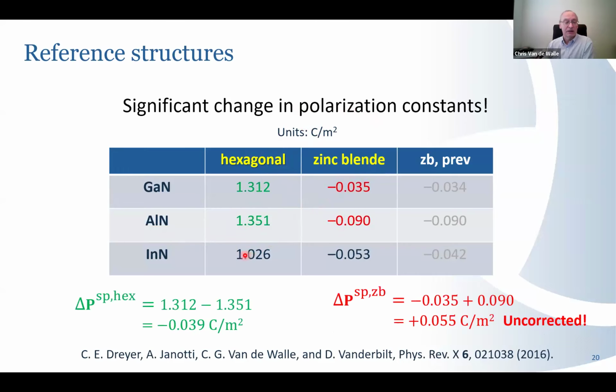And then you can say, well, we calculate these polarization discontinuities, and they're going to give different values. In fact, very different values. Referenced to the hexagonal layered structure, the polarization discontinuity for gallium nitride, aluminum nitride is minus 0.039. Referenced to zinc blende, using these values, it would be plus 0.055. So we get a totally different value with a different sign.